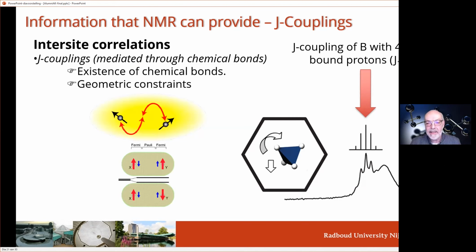The interesting thing here is that in general, J couplings in solid state, well, they are hardly ever observed in the solid state because they are minute. And the dipolar interaction is almost always bigger than the J couplings. But in this case, we see the J coupling of boron and protons, and this tells us that for this fraction of the material, the BH4 units are not only tumbling around very rapidly, they also diffuse through the whole material. So essentially, we have a fraction of BH4 that is a liquid, which is very strange, of course, to have a liquid fraction in a furthermore solid sample.